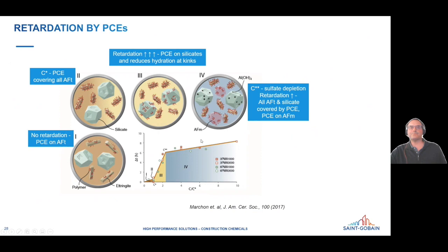In particular, they can be retarders. They are retarders. So they adsorb onto the phases inside the cement, and sometimes that causes retardation. So this is some nice work that was done about 5 or 6 years ago by Marchon. What they're showing in the inset plot here is the concentration of the water reducer on the x-axis and the set time delay, so how many hours of increased set time you have, on the y-axis. And so in phases 1 and 2, the PCE is adsorbing onto the ettringite phase, the AFt phase, which doesn't really cause much retardation. Then once that's completely covered, it starts to adsorb onto the silicate phases, which are the ones that are trying to hydrate. And that does cause retardation.